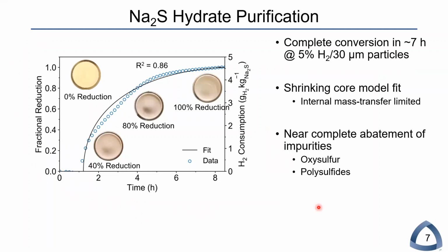In addition to this, we also showed that the reaction kinetics were well fit by a shrinking reacting core model with strong internal mass transfer limitations. And the result of this process was nearly complete abatement of the oxysulfur and polysulfide species. And the purity is nicely represented by the color change of the material from a bright yellow to nearly pure white.